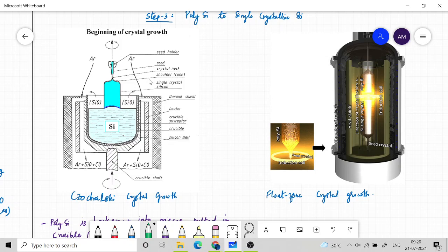You can't achieve a vacuum beyond a level. You can take out all the gas, but that will vary the pressure at which this entire process functions. So if pressure is important, you cannot do the process in a vacuum. To keep the contaminants away, one approach is to keep the entire thing inside a vacuum chamber, but that is not always feasible when the reaction requires a certain amount of pressure.